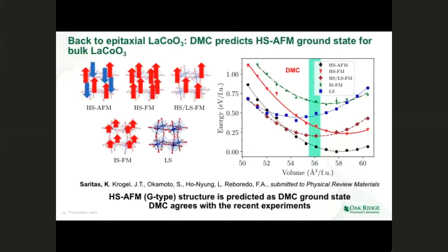So here is again the diffusion Monte Carlo calculations that we performed on these cells. In comparison to all the DFT calculations that we did, it contradicts the first model that I discussed from the experimental perspective, but it agrees better with the second, more recent model that we are seeing, basically an antiferromagnetic ground state for the bulk lanthanum cobaltite. And the energy difference between the antiferromagnetic phase compared to others is larger than when we did the PBE plus U calculations.